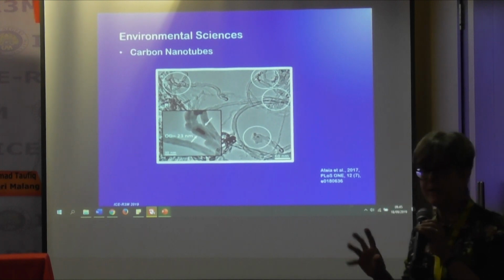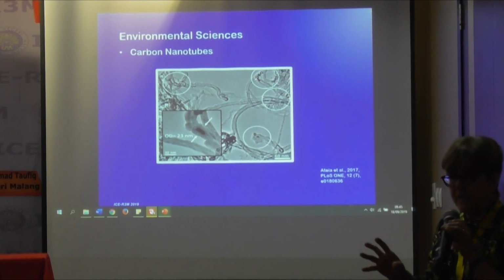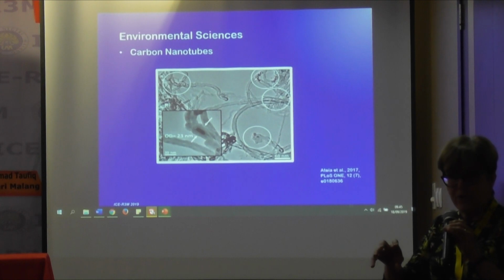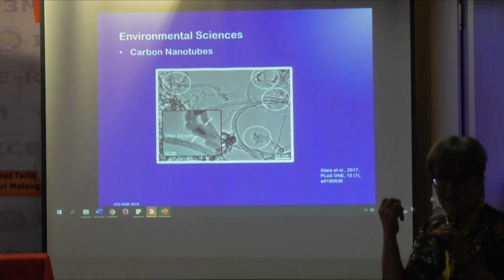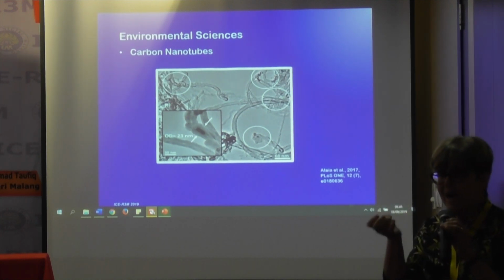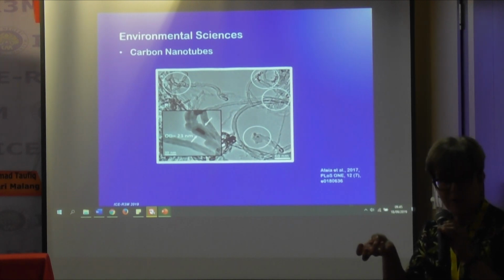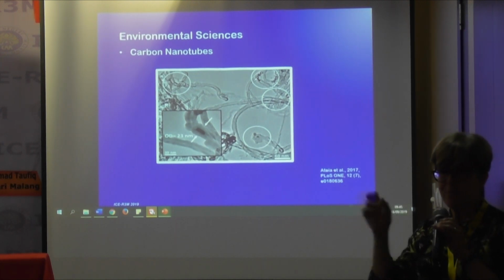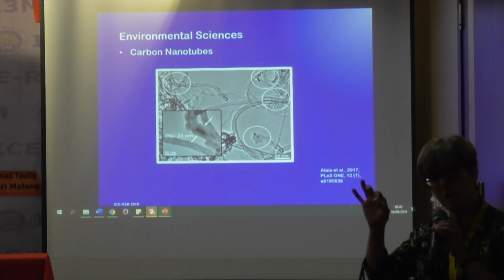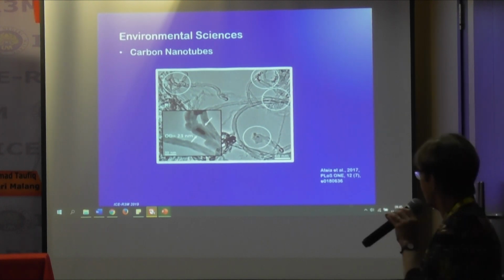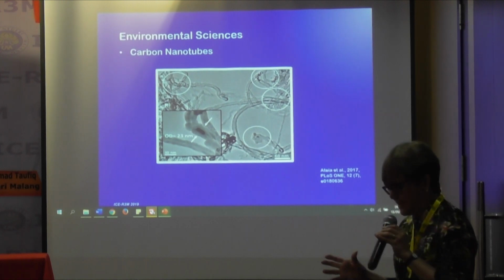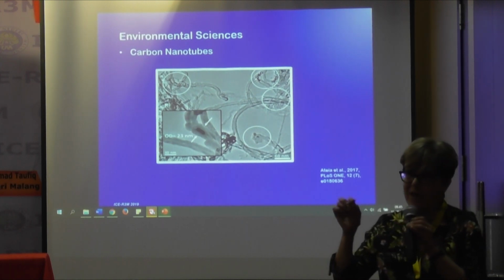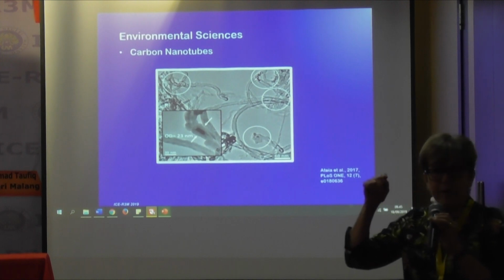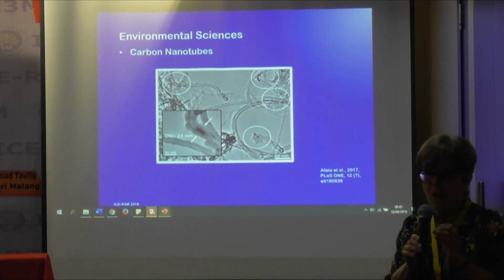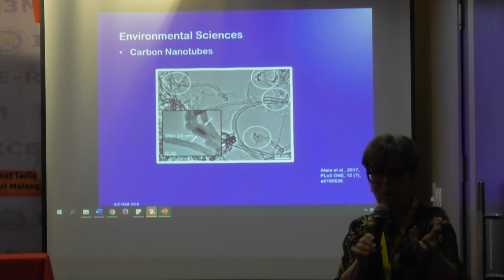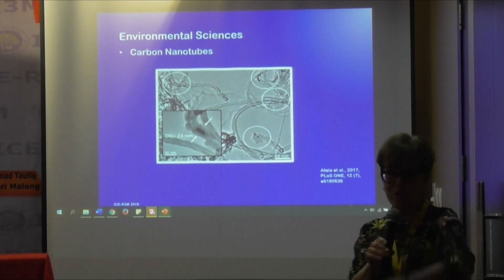And so these carbon nanotubes are being developed for use for things like soil remediation or water remediation. And then the idea is, once you put these carbon tubes in, you want to also be able to take them back out of the system. So the idea is to combine them with magnetic nanoparticles so that you can magnetically separate out the magnetic nanoparticles in the carbon tubes and the pollutant. One of the problems is that putting magnetic nanoparticles into these carbon tubes almost generates as much wastewater and contaminants as using them.